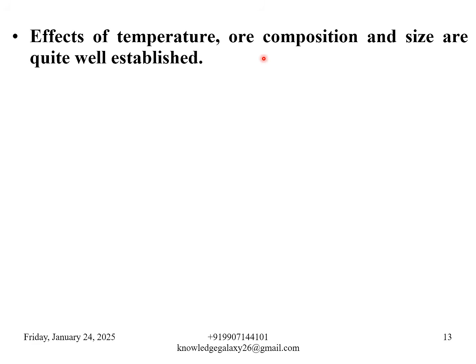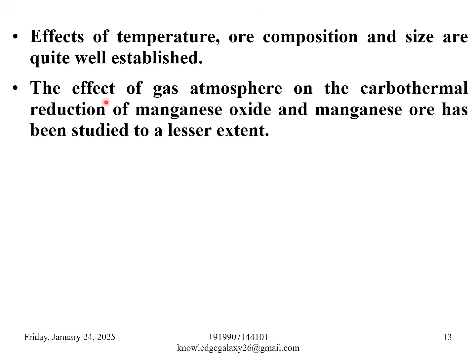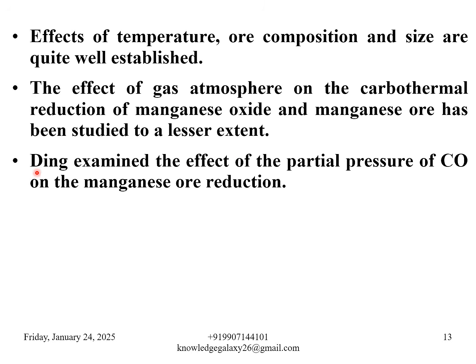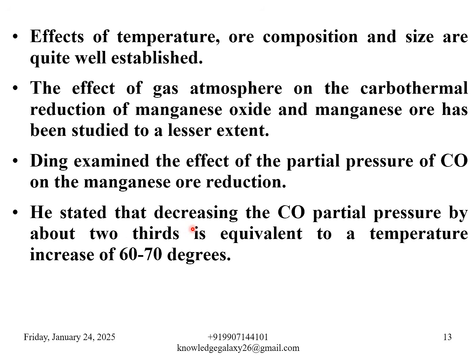Effects of temperature, ore composition and size are quite well established. The effect of gas atmosphere on the carbothermal reduction of manganese oxide and manganese ore has been studied to a lesser extent. Ding examined the effect of the partial pressure of carbon monoxide on the manganese ore reduction. He stated that decreasing the carbon monoxide partial pressure by about 2/3 is equivalent to a temperature increase of 60 to 70 degrees.